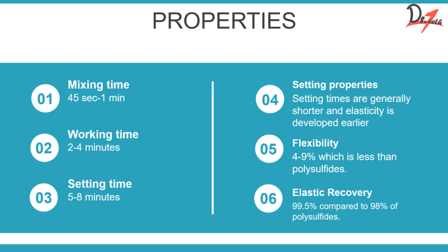Regarding time properties: mixing time is 45 seconds to one minute, working time is two to four minutes, and setting time is five to eight minutes. These values depend on temperature, and also on how accurately the correct amounts of base paste and catalyst paste have been dispensed.